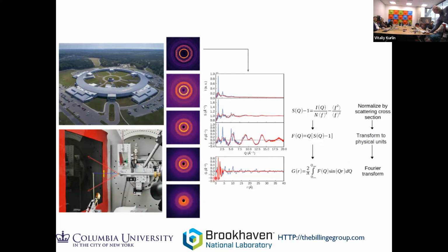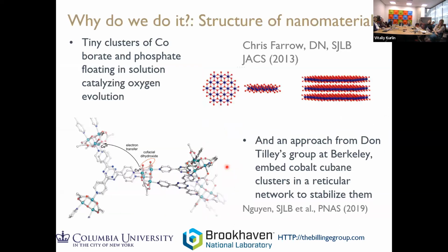And so you see very sharp peaks down here, which are very well defined local order. But because it's not periodic and perfectly in registry, as you go further out, there are rotational, orientational disorder and B factors and things, and finally it ends up with the average density. So this is the pair distribution function. It's experimentally accessible, and we can also calculate it directly from a structural model, so we can do regression.